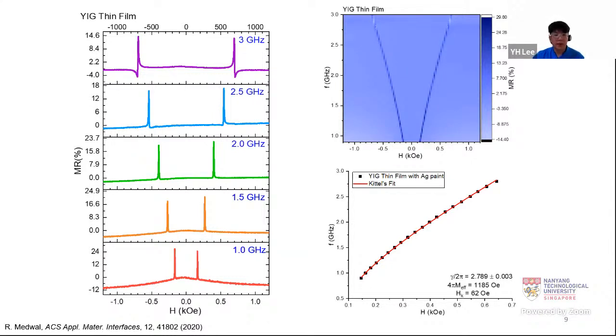But this time, for my case of study, I put the thin film onto the same MI probe sample, covering the silver paint on the top and the side. Shown on the right-hand panel is again the MI experiment, the magnetoresistance data. We can see that the symmetrical peak about the zero field is still there for all the frequencies. If we increase the frequency, the peak shifts to higher field values, in accordance with what we saw in the ceramic samples.